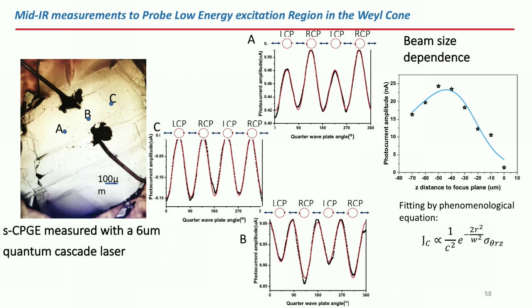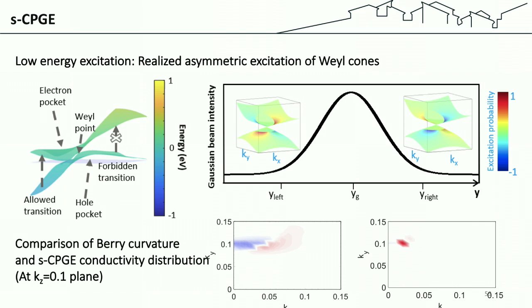All right. So recently we extended the experiment to very low energy excitation, like 6.2 microns, where we are very close to the Weyl cones, where very interesting things happen. And the most important thing is the response actually becomes 10 times stronger. That is because the Berry curvature close to the Weyl cone actually has a singularity, so it's very, very large. So now we are also probing the very large Berry curvature of this system.